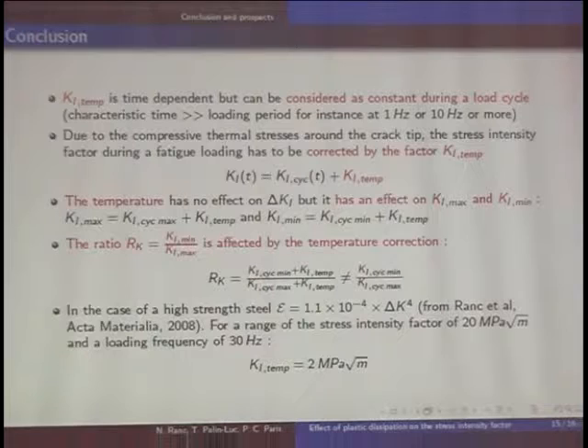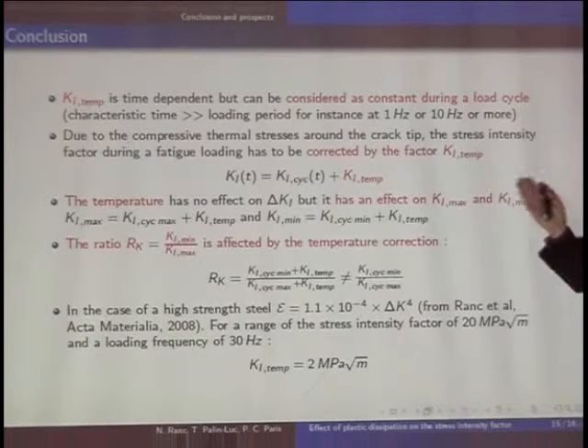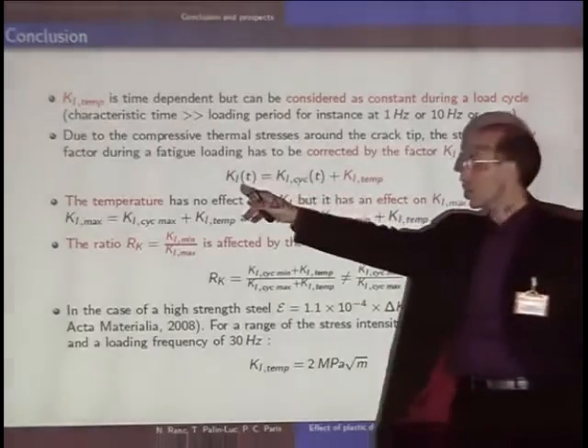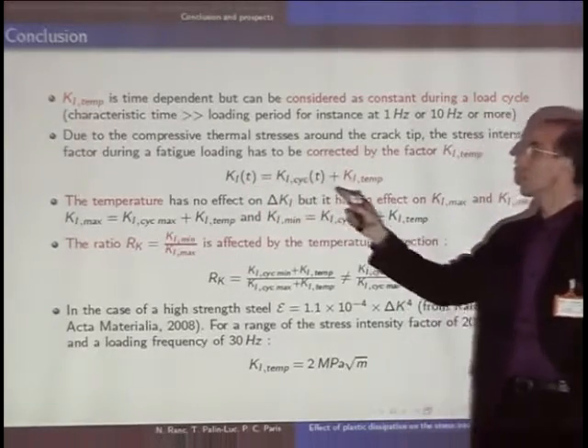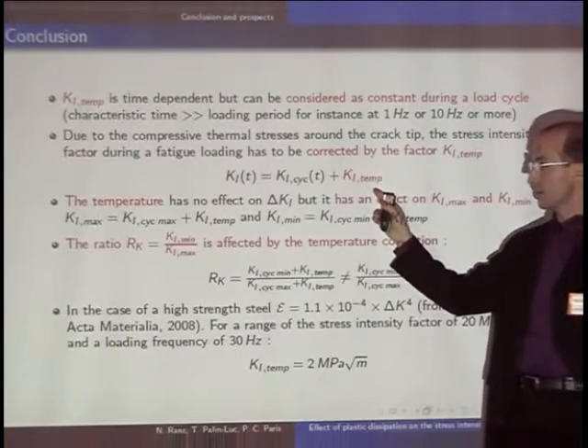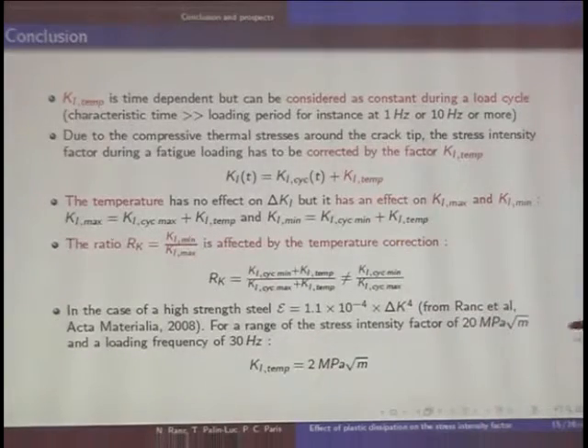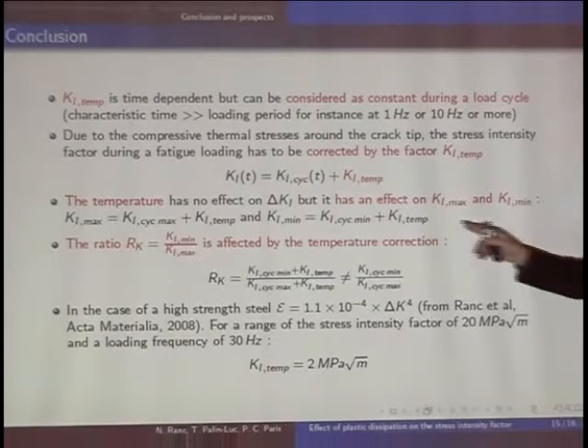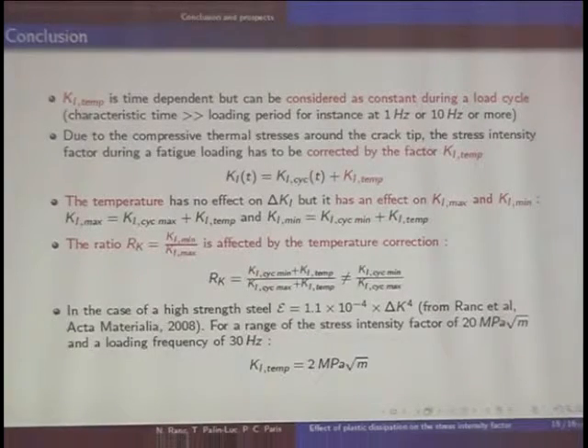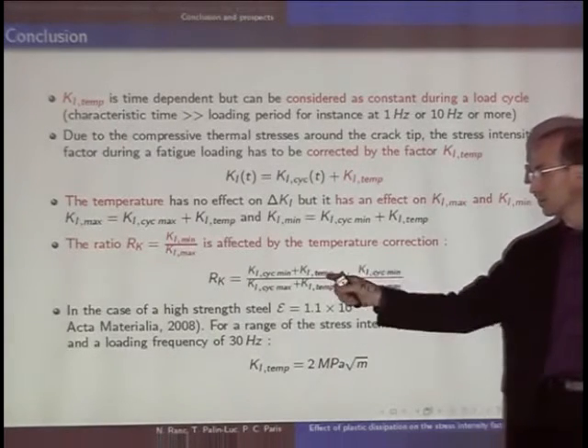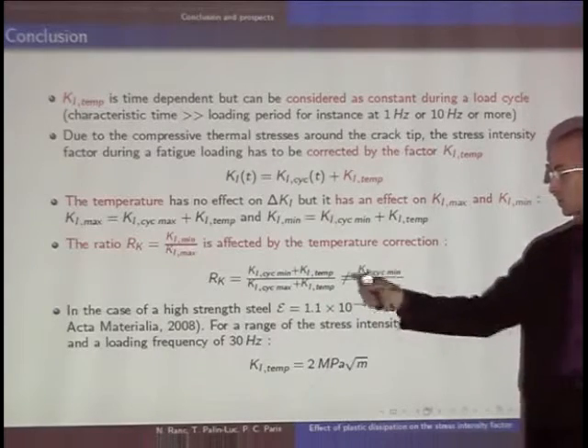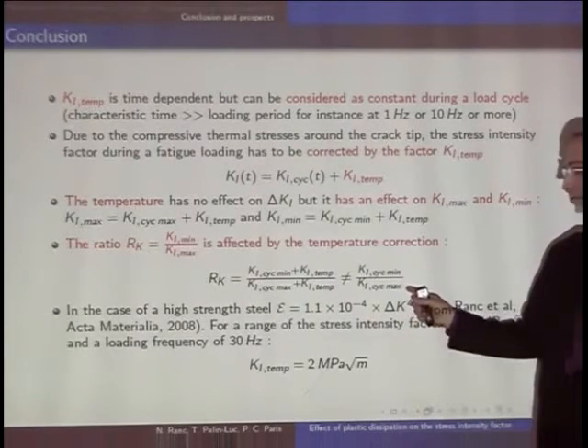period. The other point is that due to the compressive thermal stresses, the stress intensity factor under cyclic loading has to be corrected by a factor, and then consequently, if you look at the value of Kmax and Kmin, the minimum and the maximum value over one cycle is affected. There is a change. And then, in fact, if we consider the heat effect at the crack tip, the local R ratio is not equal to the common value. It has to be corrected by this K1 factor because of the additivity here. It's different to the K1 due to cyclic loading usually computed.